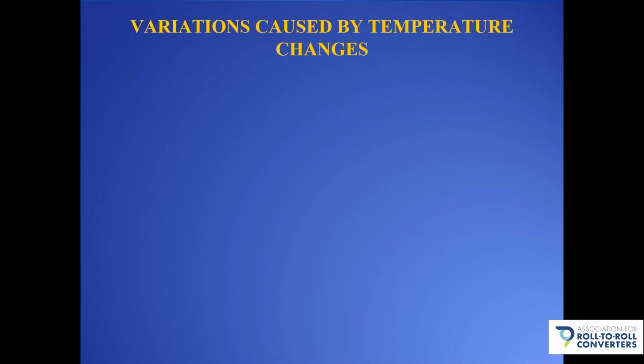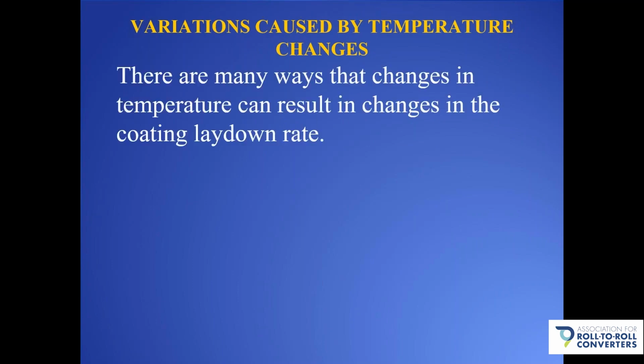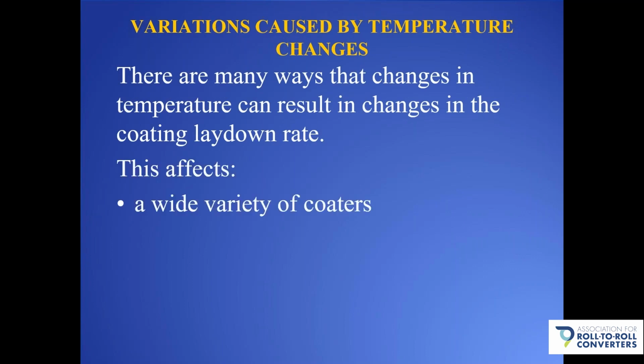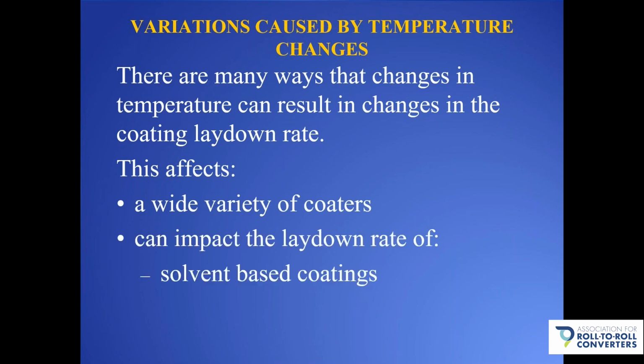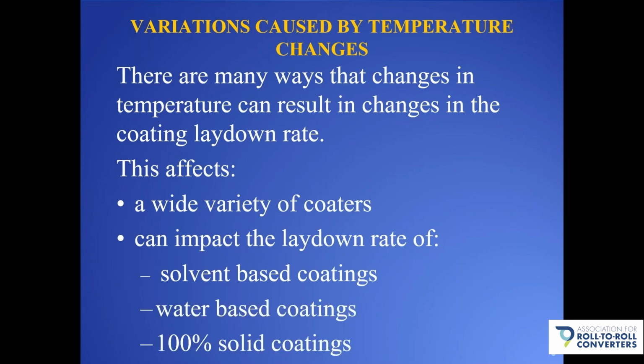So now let's move on to variations caused by temperature changes. There's many ways that changes in temperature can result in changes in the coating laydown rate. This affects a wide variety of coaters and can impact the laydown rate of solvent-based coatings, water-based coatings, and 100% solid coatings. Of particular note, we should think about 100% solid coatings and hot melt coatings, where temperature is part of the equation of delivering those hot melts, and therefore any changes in the temperature can change the coating laydown rate.